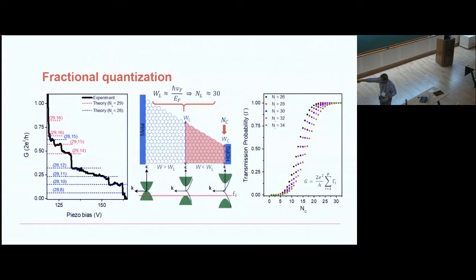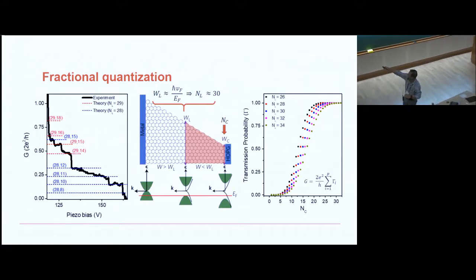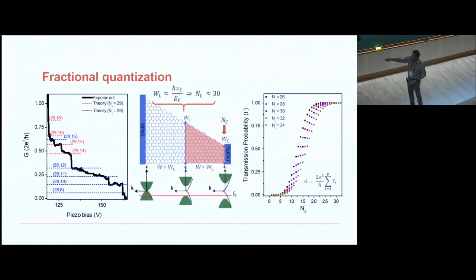Imagine as I go in this direction, the width of this is decreasing continuously, but the conductance is decreasing in steps. Okay, so what Vijay and Adif said is that what could be possible here is that these states are essentially a discrete number of hexagons that is connected to your lead. As I pull my flake out, I decrease the point contact size by units of hexagon. I can't decrease it continuously. And each of those states is essentially giving the number of hexagons that is connecting this flake, or the bridge, to the lead. Yes, but it decreases in steps.